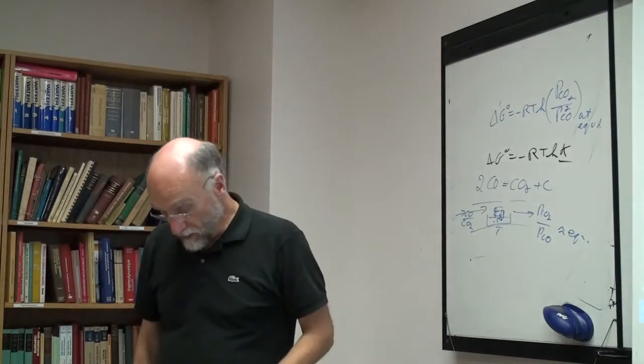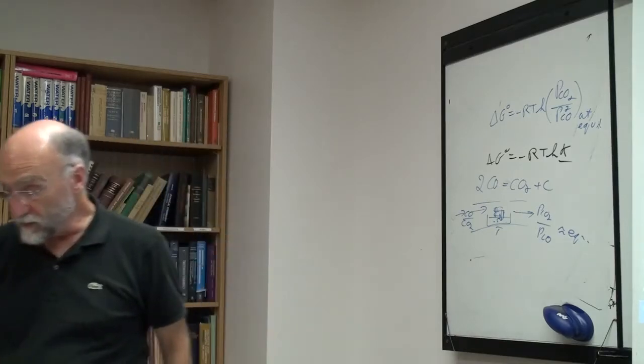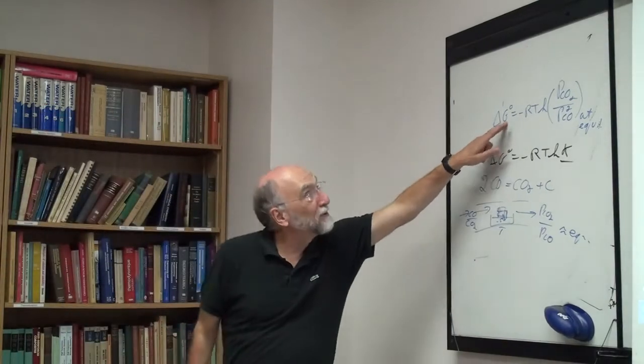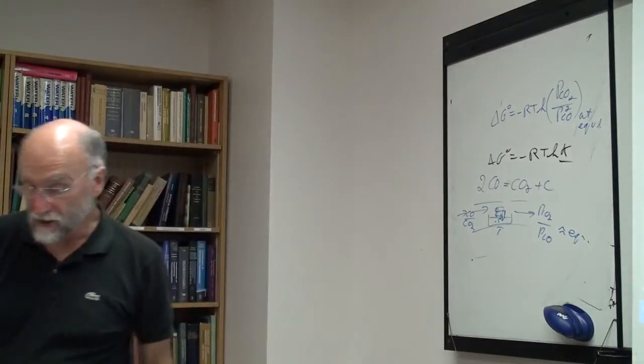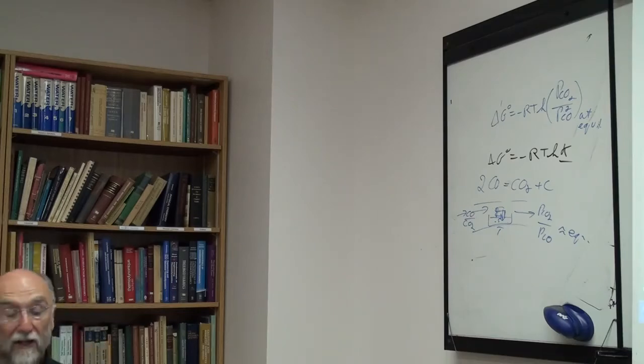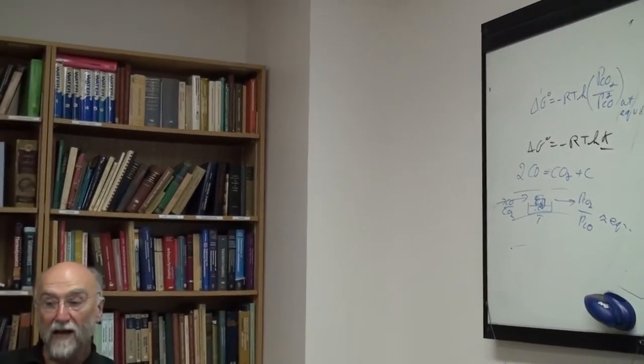So the general way is you measure the Gibbs energy change, and that gives me not the Gibbs energy change at equilibrium, but the standard Gibbs energy change. Gibbs energy changes are generally measured by establishing an equilibrium. So you can actually get delta G of a reaction without actually carrying out the reaction. You let the thing reach equilibrium and you observe the equilibrium conditions. That's generally how you get delta G. This is a simple example, but in all cases where you're measuring delta G somehow, you're setting up an equilibrium, measuring the equilibrium conditions, and then working backwards to get delta G.